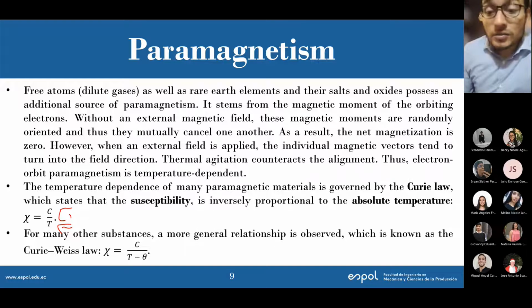And in general, metals, with only a few exceptions, do not obey the Curie-Weiss law. So this law doesn't apply to most metals. Only a few metals like nickel, for example, follow this law. Iron also follows this law. But other metals usually don't follow it. Carbonates, chlorides, sulfates, yes, obviously they do follow the Curie-Weiss law.